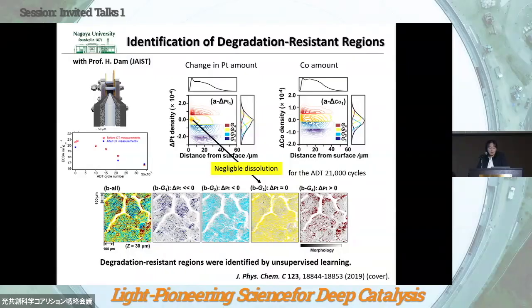And we found some strong correlation for some parameters, for example, some geometric parameters in the cathode catalyst layer, such as distance from the surface, and the change in the platinum density. And we found some part with negligible dissolution under the working conditions, this yellow one. So this kind of combination of unsupervised learning, data mining, and the imaging technique will provide some new information chemists cannot immerse in without any visualization of the materials.